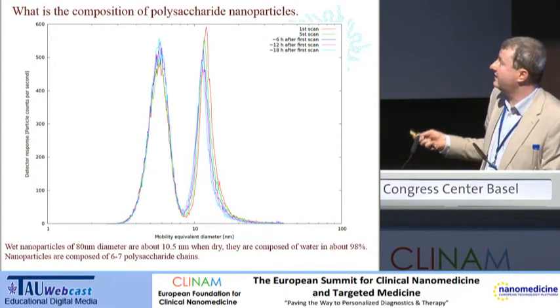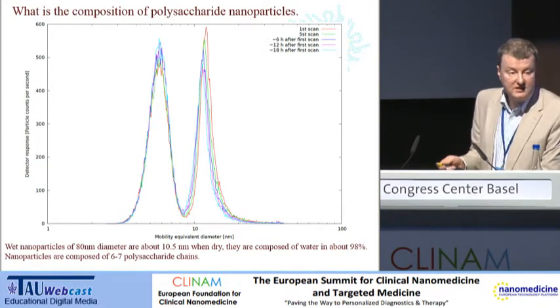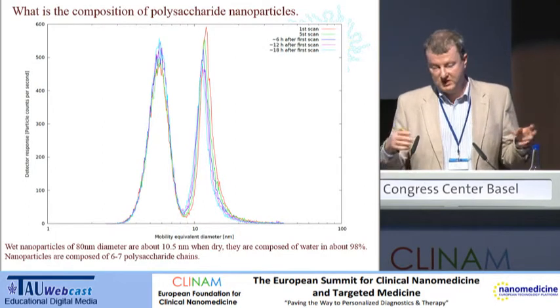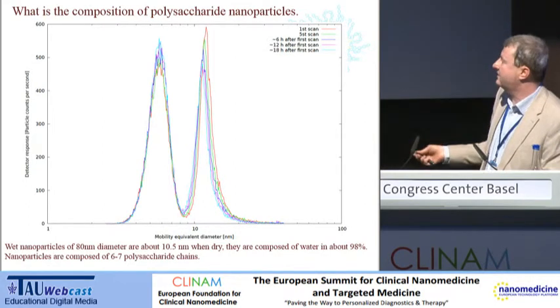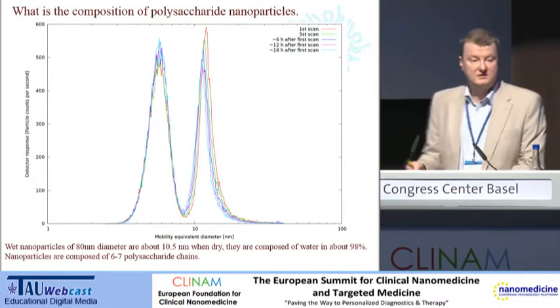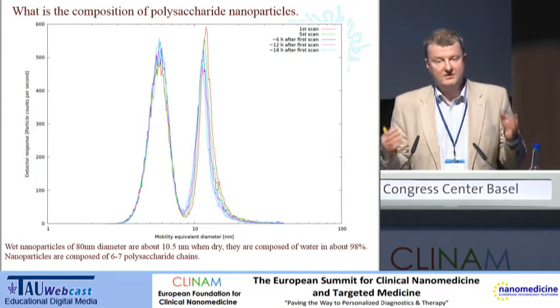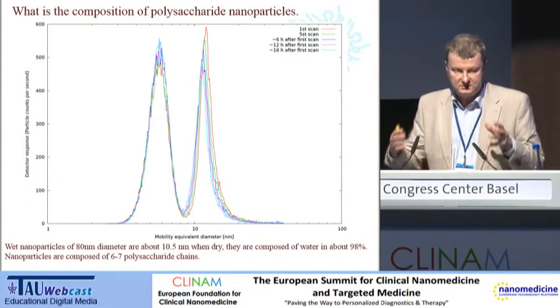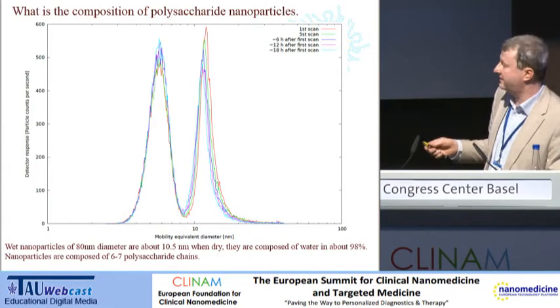Since the volume changes to the third power of the diameter, you can easily calculate the water content — it is about 98%. So you have to think that those nanoparticles are not solid. It's more of a cloud — hydrogel nanoparticles.